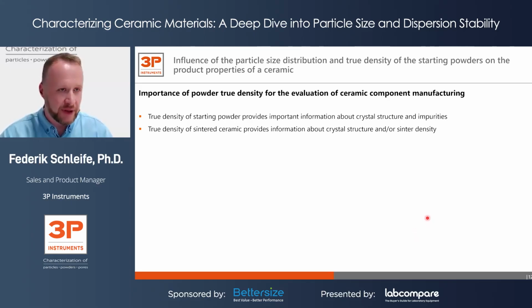So this is for the influence on particle size, but what else can we do with the powder to analyze the ceramic raw material? Another factor that affects the process later on is the true density. I want to show you how the true density can affect the starting powders, or the other way around, how the different densities of starting powders can affect later on either the process or the performance of the final ceramic pieces. And therefore it needs to be mentioned that the true density of starting powder provides important information about the crystal structure, but also impurities.